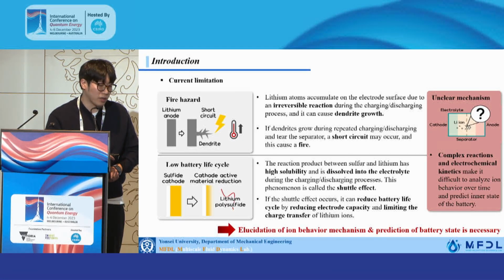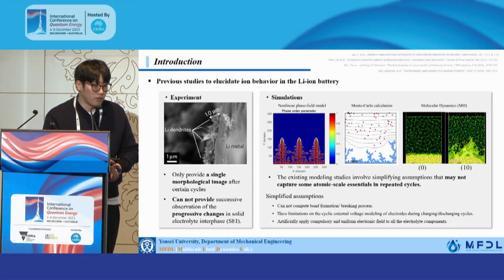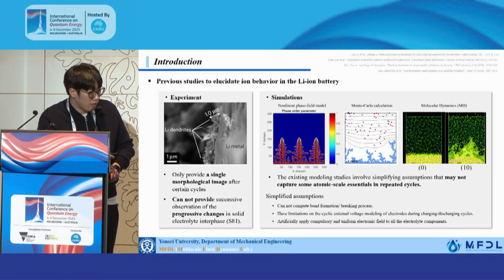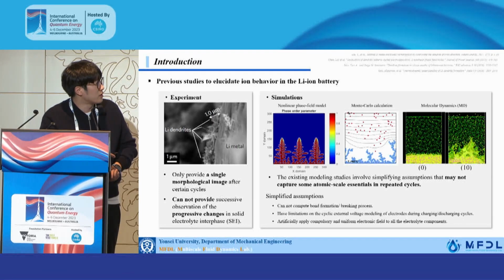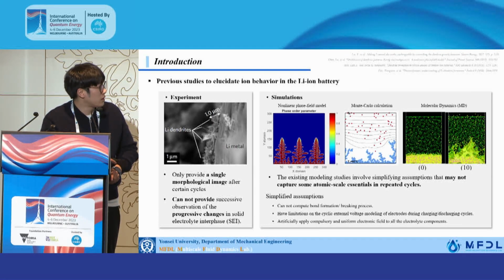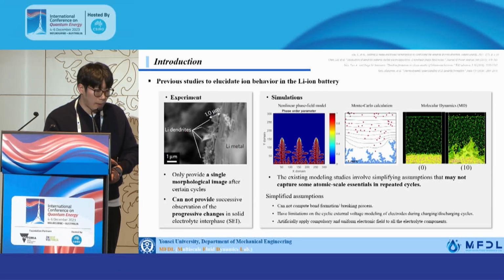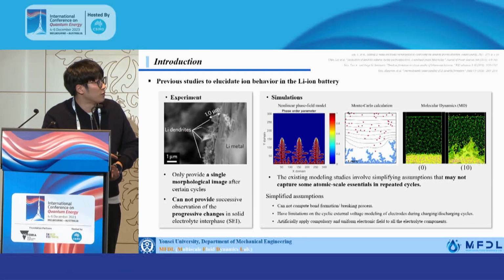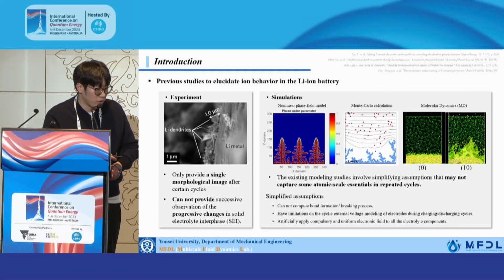Therefore, the elucidation of the ion behavior mechanism and prediction of battery state is necessary. And here are the previous studies to elucidate the ion behavior in lithium-ion battery. In terms of experiments, they only provide a single morphological image after certain cycles, and they cannot provide successive observation of the progressive changes in the solid electrolyte interface. In the case of simulation, the existing modeling studies involve simplifying assumptions that may not capture some atomic scale phenomena in repeated cycles. So with the simplified assumption, they cannot compute bond formation and have limitations in implementing repeated cycles, and they just propose a uniform electric field in the system.